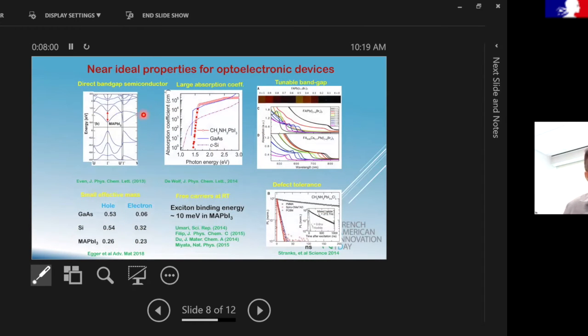Now, in addition to this, there are some other properties. For example, one thing is that these are, and I won't go into details, direct bandgap materials. They have very large absorption coefficients, which means that they can absorb sunlight very effectively. And you need a very thin layer to do that. You just need about 500 nanometers of a film, and they should be able to absorb all of the solar flux that is incident on them. Okay. Another thing that is quite nice about these materials is you can tune their color. You can tune the color by changing the chemistry. You can get different concentrations of these different components and change the wavelength at which they absorb.